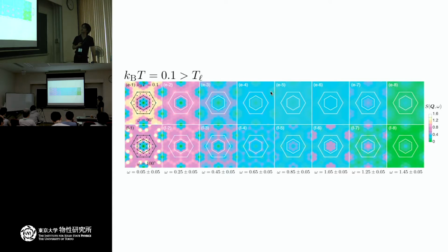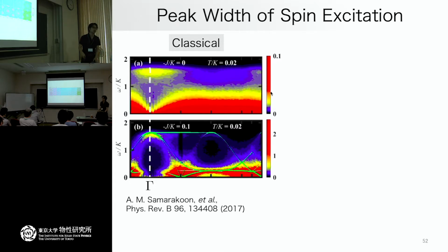And if you lower the temperature, it's still larger than the low temperature scale, but we already have some signature of the magnetically ordered phase in this lower data, because this bright spot corresponds to the zigzag order, which should be observed in the zigzag magnetically ordered phases.